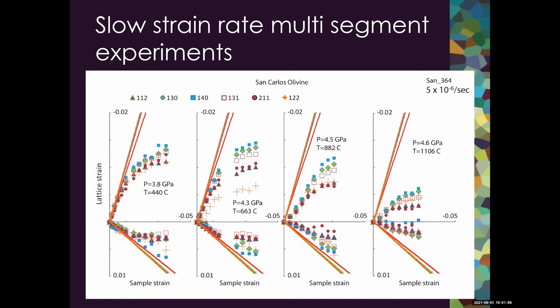And so this was a multi-segment experiment performed up to about 4% strain on polycrystalline San Carlos olivine from about 440 degrees Celsius to about 1100 degrees Celsius, with the pressure conditions just changing slightly as we're increasing in temperature. We have our powder diffraction data shown as the symbols with the diffraction from the detectors in the compression direction in the upper quadrant and the diffraction from the detectors in the transverse direction in the lower quadrant. These EPSC models are shown just as the solid lines again, correlating with the color of the diffraction data points.